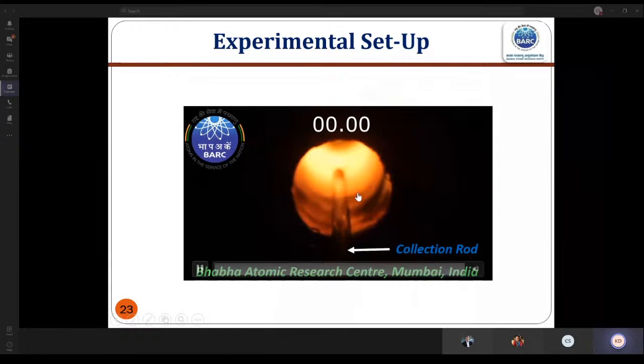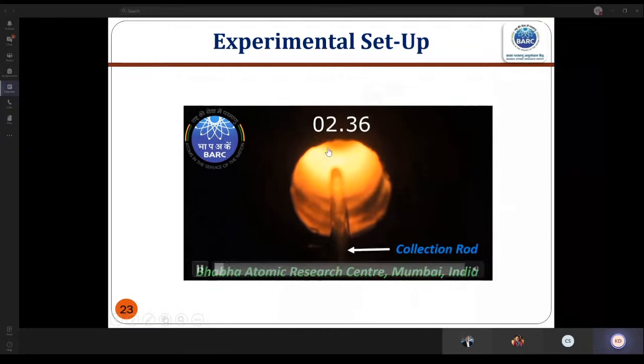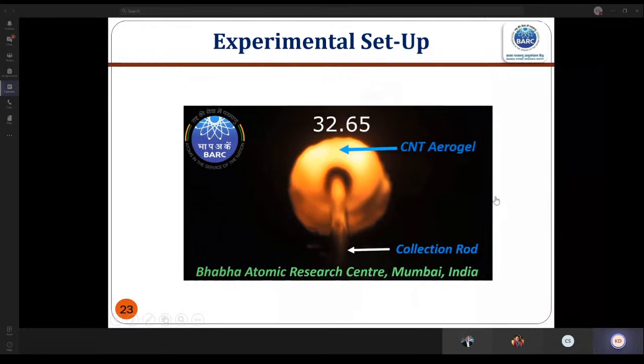So this is a typical video. Here you can see how it happens. This is inside a furnace, at very high temperature, more than 1200 degrees centigrade, and a rod is rotating. That is, from the outside we push it inside, a rod is rotating. This is where the CNT aerogel formation starts. You can see something like an agarbatti type of thing coming, which is in the gas phase. Carbon nanotube is growing, and then we can go on collecting them on the rod. So you can easily find that this is typically the growth of the CNT aerogel.